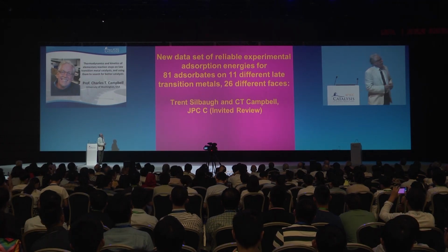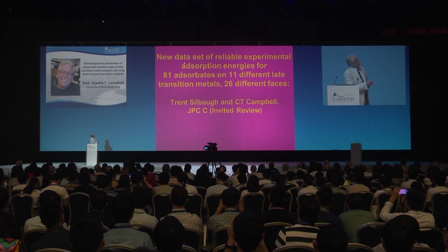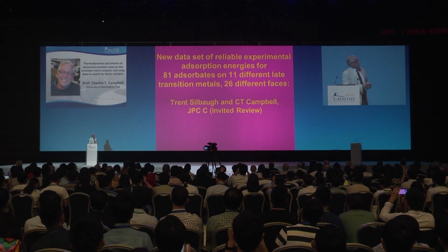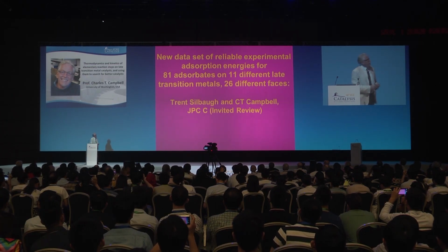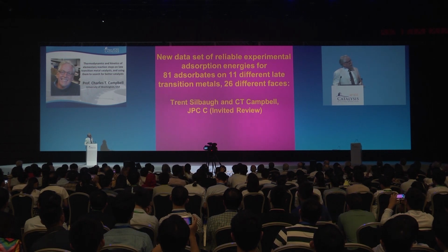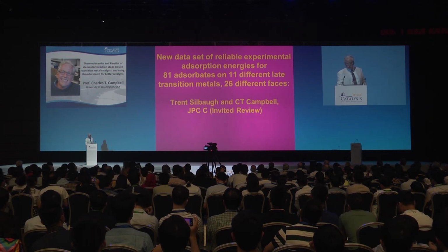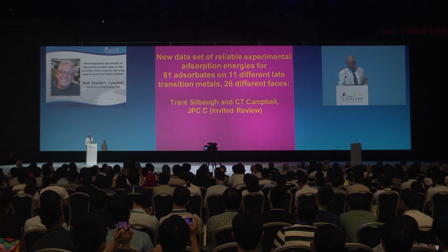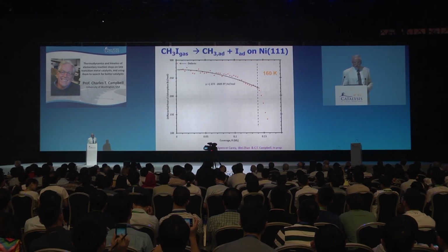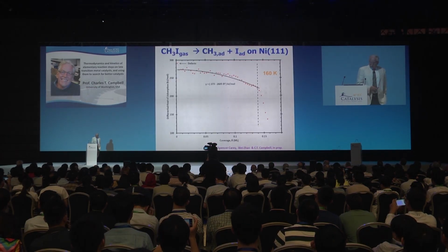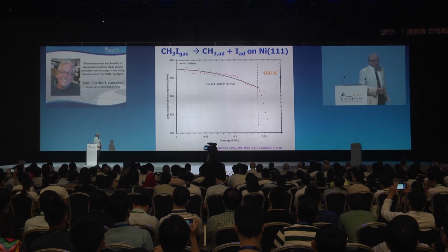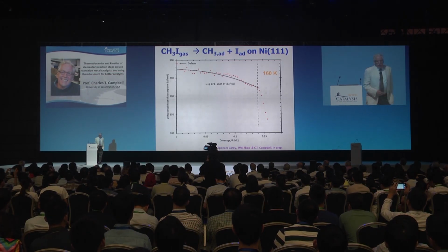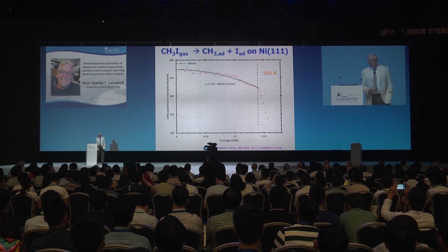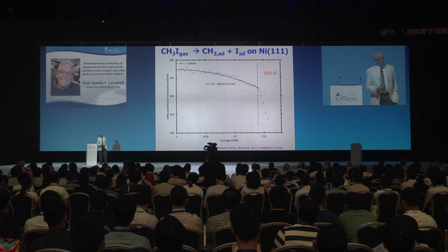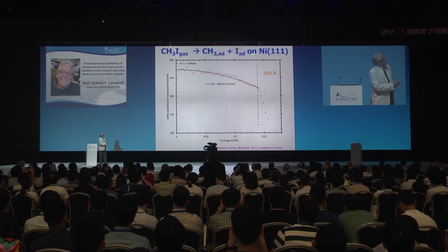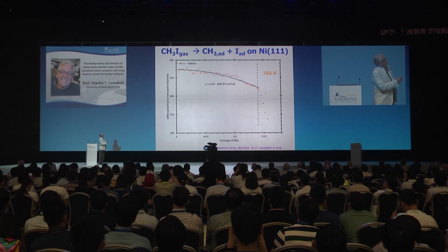We also just submitted a paper that has a larger database, 81 adsorbates on 11 different metal surfaces with 26 different faces of transition metal surfaces. So that should appear soon for those of you that are interested in databases of accurate experimental adsorbate energies. All of the molecular fragments that I talked about so far were on platinum, and so we've moved recently to nickel. And so here's an example of methyl.